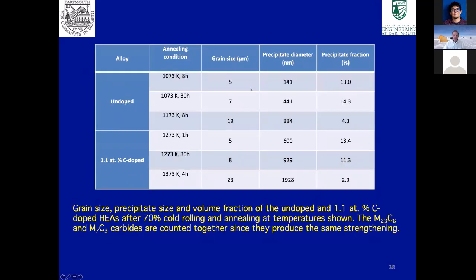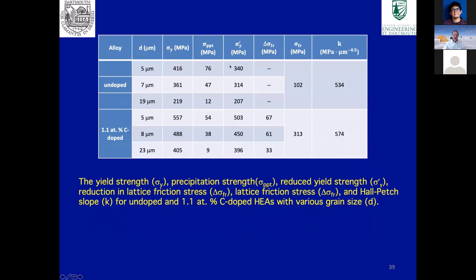And so what we did was we actually looked at the precipitate diameters we got in each case and the precipitate volume fractions. And then we could use a calculation to back out the contributions of the precipitates from the yield strength of the alloy. So this is the yield strength we measured. We could calculate what the precipitate contribution was, and then get a yield strength without precipitation strengthening to replot the whole Hall-Petch relationship.